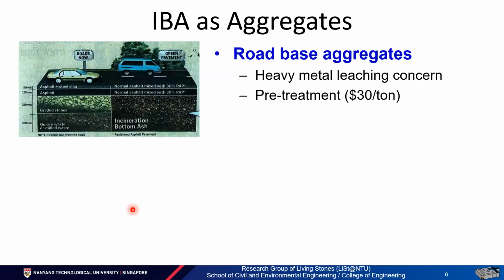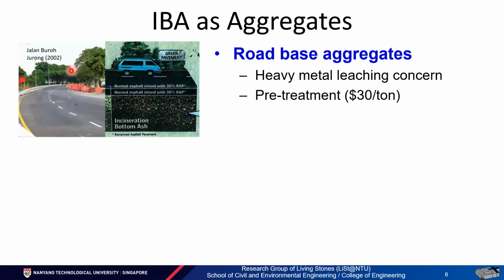From the literature, IBA is mainly used as aggregates, and most of the time as secondary aggregates because of the lower strength grade compared to natural aggregates. Even locally this has been tried: in 2002, in a stretch of road in the west part of Singapore, the base course was built using IBA as aggregates. However, at that time the major concern was heavy metal leaching.